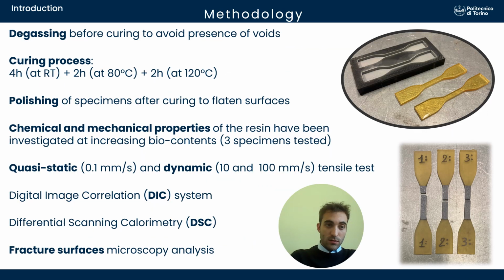The methodology consisted of a degassing phase before curing in order to avoid the presence of void into the resin mixtures, followed by a 3-stage curing process, and after that the surfaces of the specimens were polished in order to flatten the surfaces. Chemical and mechanical properties of the resins have been investigated at increasing biocontents by means of quasi-static and dynamic tensile tests, by means of a digital image correlation system in order to acquire the strain data. Moreover, a differential scanning calorimetry analysis was performed on already cured specimen in order to verify the complete cross-linking of the resins. And finally, the fracture surfaces were analyzed by means of a digital microscope.